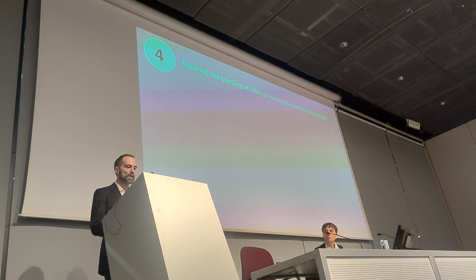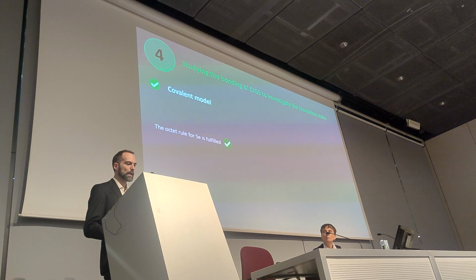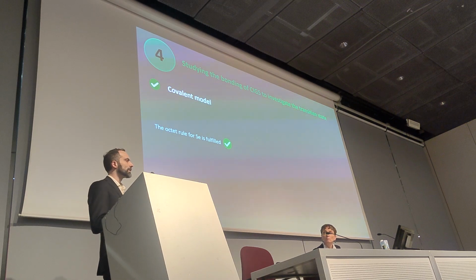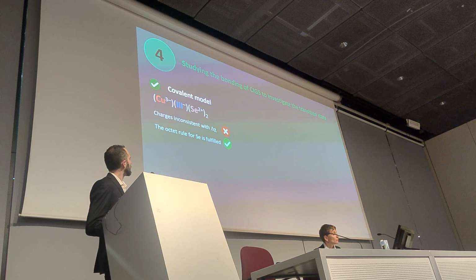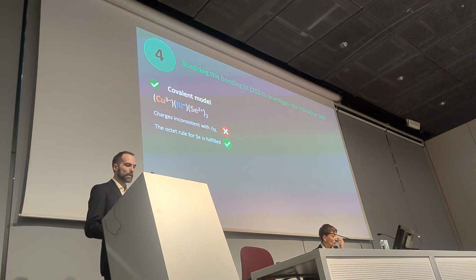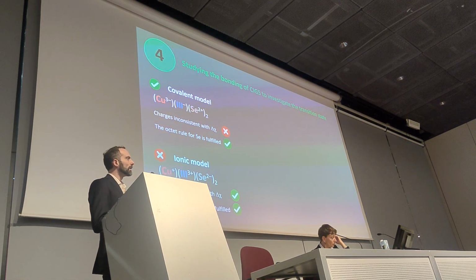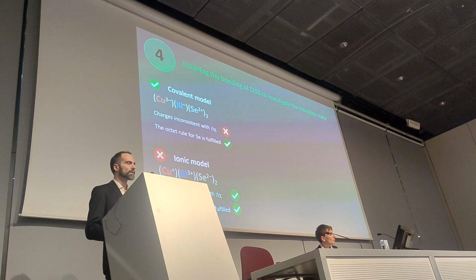So we are now trying to study the bonding of CIGS from a chemical point of view to, in the future, hopefully unravel what is happening in the transition state, this catalytic step. So we can describe the CIGS with two different models, of course. A model that satisfactorily describes the physical properties of CIGS, a covalent model. However, what we have is inconsistent formal charges. On the other hand, we can go for a wrong model. It's not an ionic compound, CIGS, but if we do consider that, we get at least consistent formal charges.